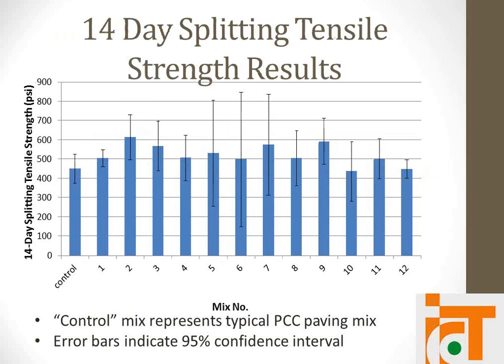Splitting tensile, the variability for this test is quite large. One thought is that we're compacting in the vertical direction, and we're unsure of the horizontal compaction that's occurring, so splitting it on its side is going against the direction of compaction. That's one thought process. But they all compared similar or greater than the control mix.